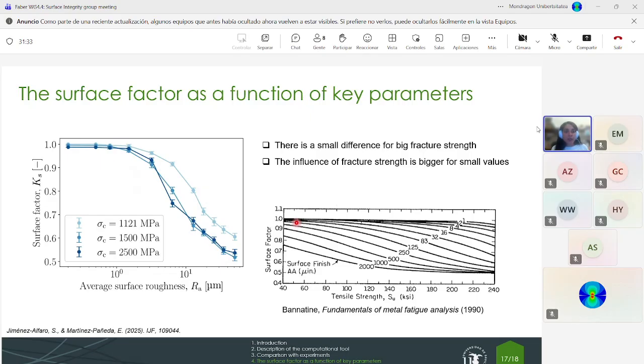We have also analyzed the influence of another parameter, the fracture strength. And here I need to make an important comment: for the fracture mechanics community, especially for those working in brittle fracture, the fracture strength is the most important parameter. And since the phase field model was created in this brittle environment, we use the fracture strength as an input. But when we go for metals, the fracture strength is not very well determined. We don't measure the stress level at which we have fracture. We normally measure the tensile strength, the ultimate strength, that is the maximum stress level that we can get in the tensile test.